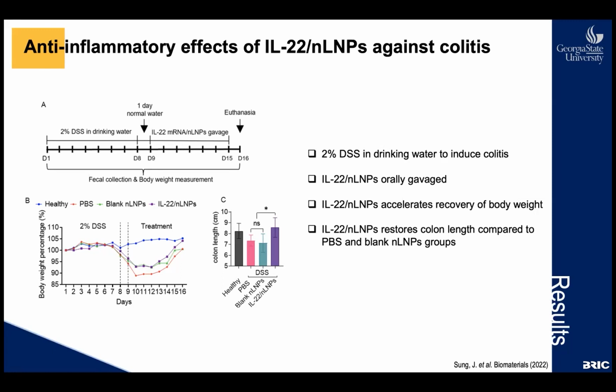The first anti-inflammatory parameters are body weight and colon length. Compared to the blank lipid nanoparticles and PBS-treated groups, the IL-22 lipid nanoparticle group showed restored body weight close to the healthy group, and the colon length of mice treated with the IL-22 lipid nanoparticle was also longer than the other groups.